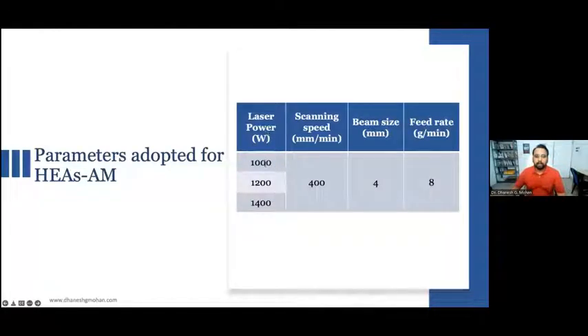These are the parameters we adopted for our experiment. The laser power we adopted was 1000 watt, 1200 watt, and 1400 watt, and we kept all the remaining parameters constant. That is, scanning speed is 400 millimeter per minute, beam size is 4 millimeter, feed rate is 8 grams per minute. By using these parameters, we fabricated three materials, and by using these three combinations, we made three substrates.